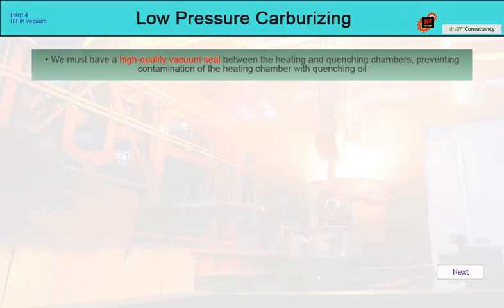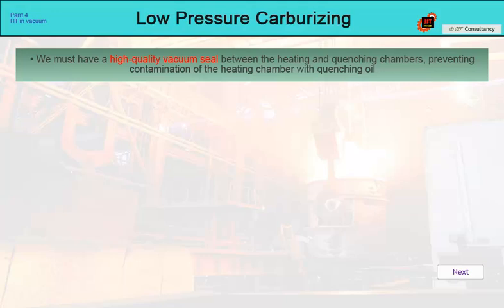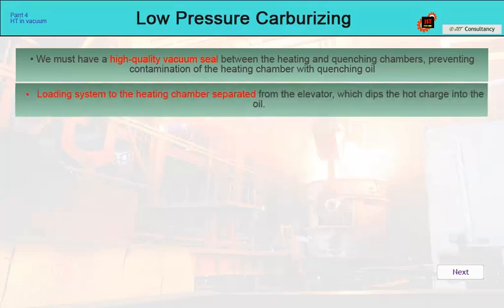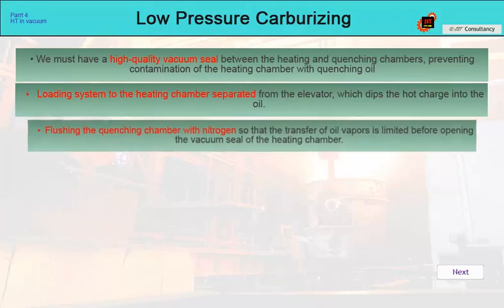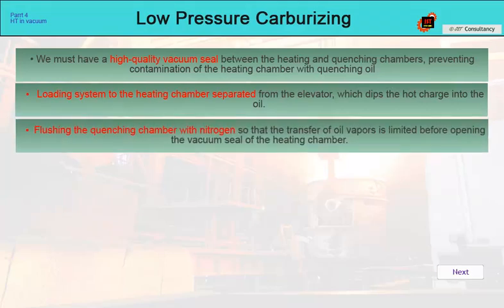To prevent these phenomena, we must respect certain principles when designing a furnace for LPC. We must have a high-quality vacuum-sealed door between the heating and quenching chambers, preventing contamination of the heating chamber with quenching oil. Loading system to the hot zone must be separated from the elevator, which dips the hot batch into the oil. For each batch loaded through the conveyor system contaminated with quenching oil, we can introduce oil residues into the heating chamber. Flushing the quenching chamber with nitrogen so that the transfer of oil vapors is limited before opening the vacuum seal of the heating chamber.